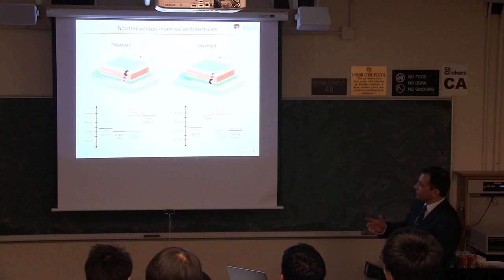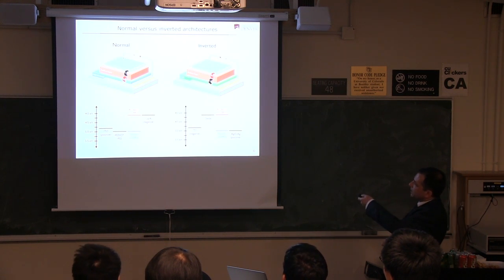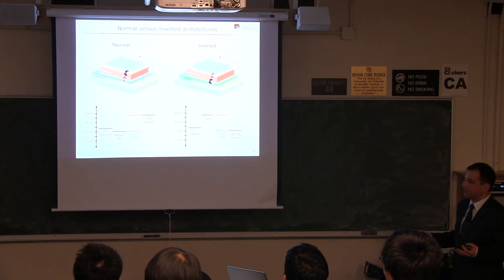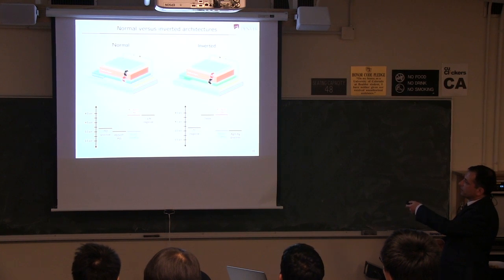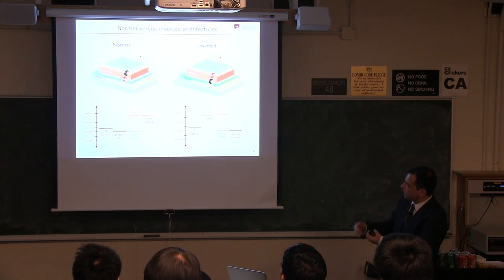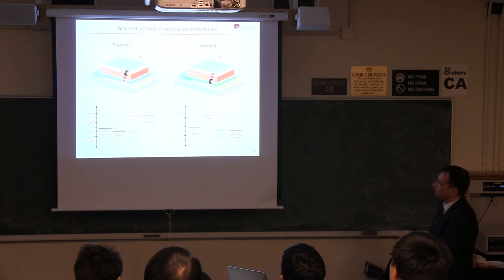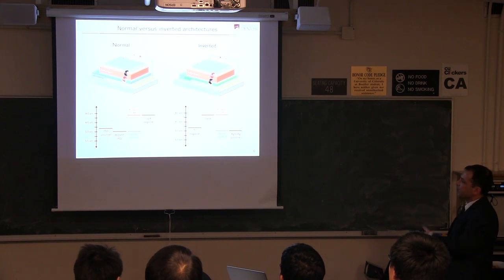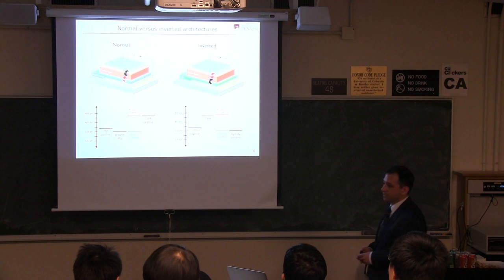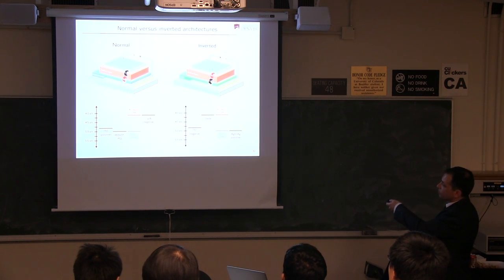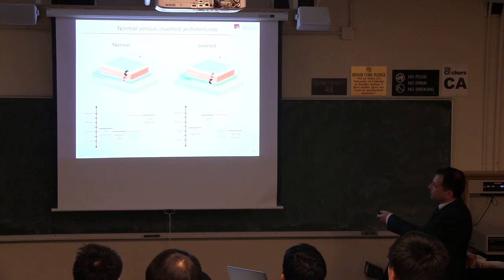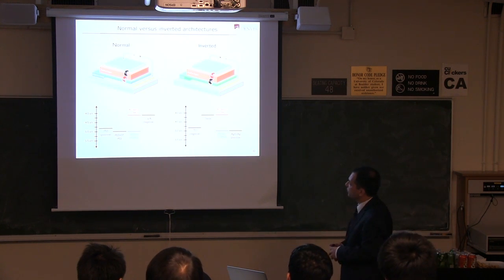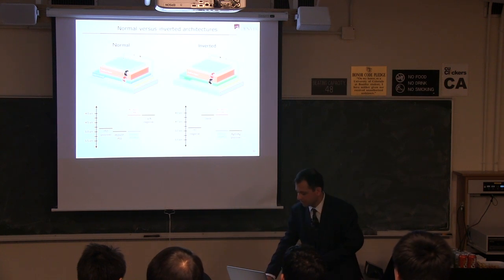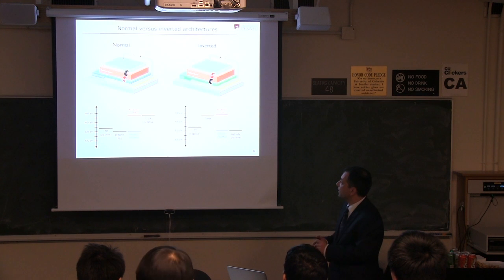One thing we do a lot at NREL is invert the geometry of the device. And to do that, you put in a buffer layer that only transports electrons. Zinc oxide is an excellent example of that. And so this lines up well with the conduction band of the acceptor, and therefore selectively takes electrons from the acceptor eventually through the ITO. Then we can use silver on the other side. And what happens is that silver oxidizes also quite rapidly, but it's very beneficial oxidation in this case. So as it oxidizes, it goes from a vacuum work function of about minus 4.1 all the way down to minus 5 or even lower. So it turns out to be a perfect positive electrode that's already oxidized. It's pre-oxidized, so it's going to do well in air. So for a device that is industrially relevant, that is really robust in air, this is the geometry you'd like to use. Okay, so that's kind of just a rapid overview of OPV.